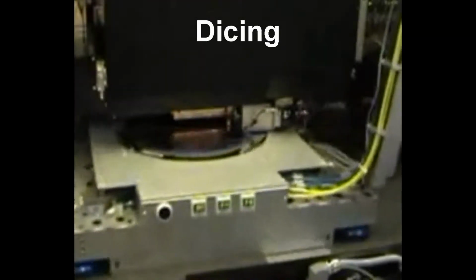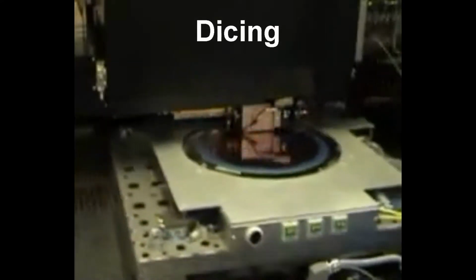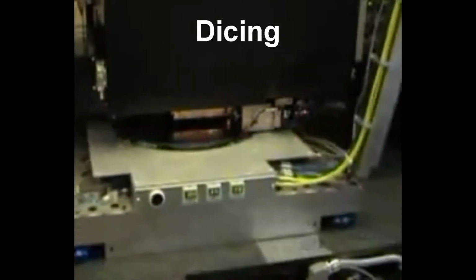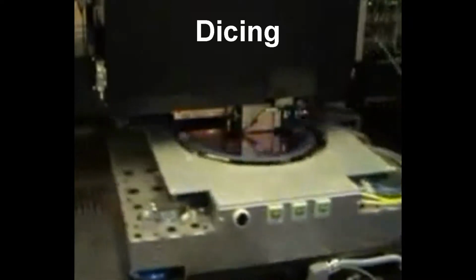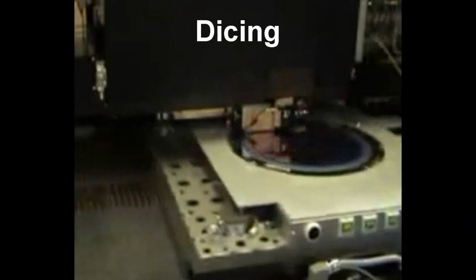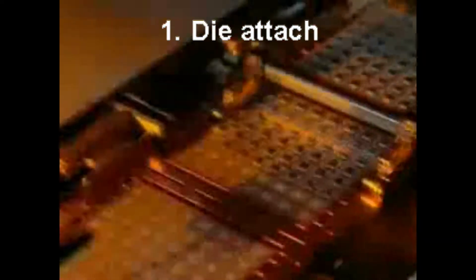The front end, where the silicon wafer is treated as a whole, ends with the dicing of the wafer, where the chips or so-called dies get separated by a diamond blade or a high-power laser. The die attach is the first of the three process steps in the back end of line. The chips are picked up from dicing foil and bonded to a conducting substrate, the so-called lead frame.